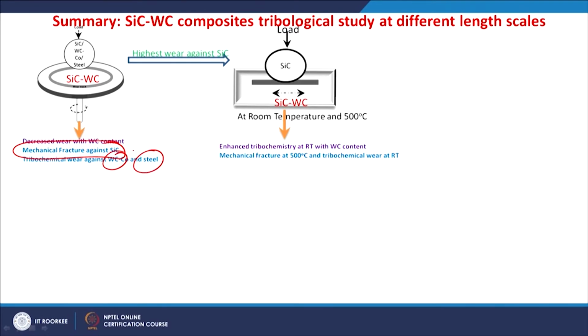So, in case of reciprocatory sliding conditions, which were done in silicon carbide against silicon carbide ball only, they again showed an enhanced tribochemistry. So, you can see the mechanical fracture against silicon carbide in unidirectional conditions actually changed to a tribochemical induced wear at room temperature for these composites, whereas at higher temperatures again the mechanical fracture is dominant.